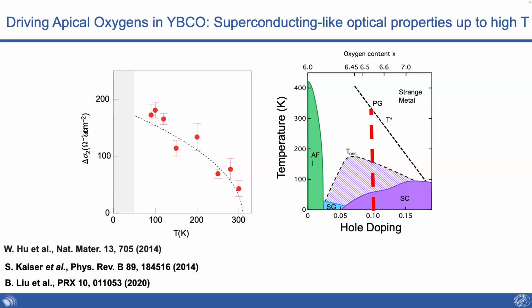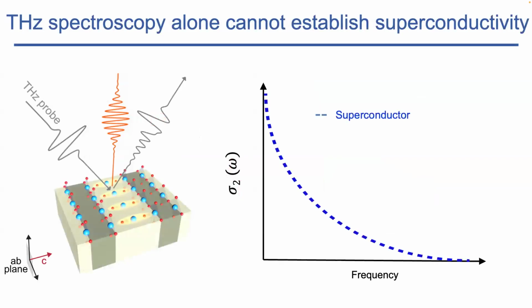Now, it turns out that what I just told you is a necessary but not sufficient condition for superconductivity. And let me tell you why. This is sigma 2, the imaginary part of the conductivity for a superconductor. It diverges like 1 over omega. Basically, it's inductive transport, so impedance is proportional to omega. Now let's take a metal that has very high mobility, so a very low scattering rate. Sigma 2 will look, for all the frequencies higher than the scattering rate, basically like a perfect conductor, so it will be inductive. It means that the charge is accelerated when you apply an electric field. But then when you reach 1 over tau, this thing will roll over.